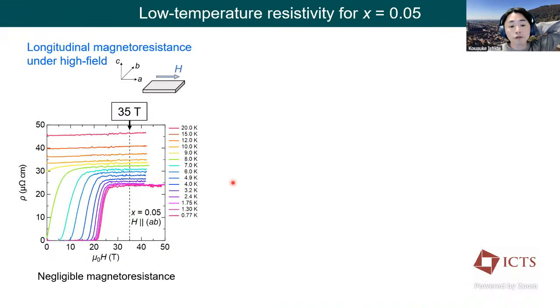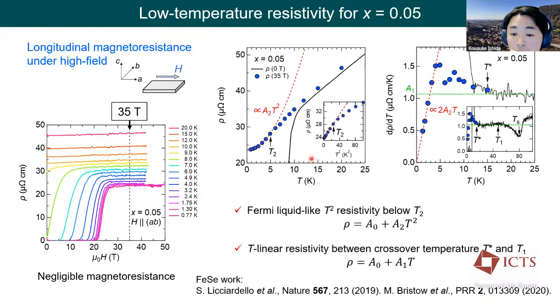So we applied a high magnetic field to destroy the superconductivity and tried to see the normal state resistivity below Tc. And here the field is applied in the ab plane. In this longitudinal configuration, the magnetoresistance is negligible. This is the data for x = 0.05, so with just a small tellurium substitution. And the resistivity shows a T-square dependence, expected in a Fermi liquid ground state, below 5 Kelvin. On the right side, I show the temperature derivative, and it becomes flat above the crossover temperature T star, and it continues to T1. So this corresponds to the crossover from the Fermi liquid ground state to the T-linear resistivity regime with increasing temperature.